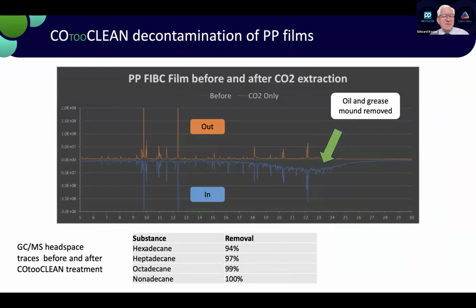And these two traces are GCMS headspace traces, showing that on the blue trace underneath, the peaks are representing molecules that are present in the polymer, and you can see the trace, the orange one afterwards, shows you a much flatter trace, especially in the longer residence times, showing we can remove oils and greases, which is something which is quite unique. Many decontamination processes struggle to remove high molecular weights, whereas this process actually is very efficient with those materials. And at the bottom, you can see other hydrocarbons, which are typically in polymers are also removed at high removal rates. And the residual peaks you see there are characteristic of polypropylene, so coming out of the polymer itself, which are conventionally always there.